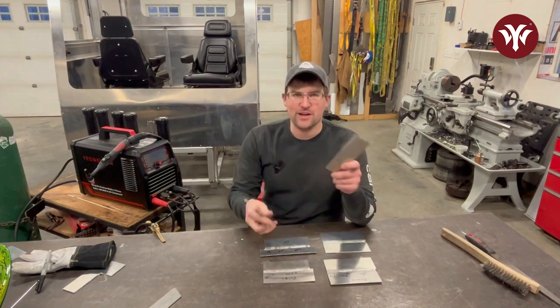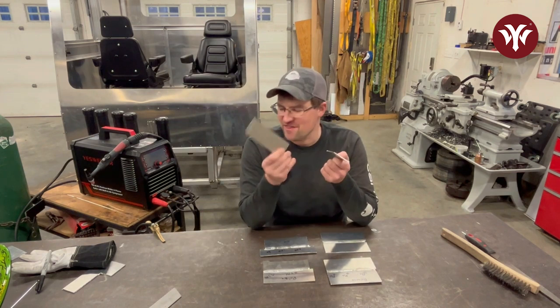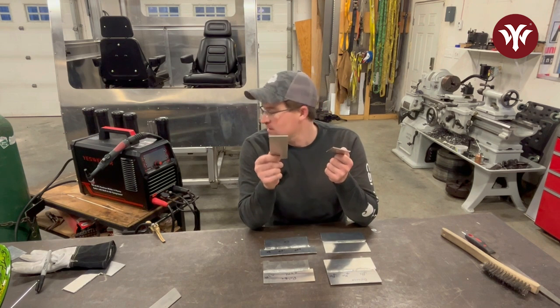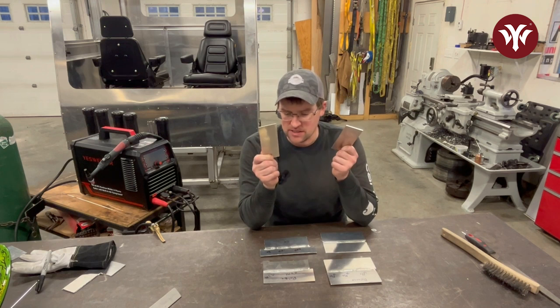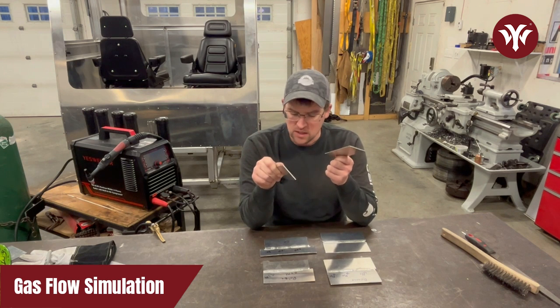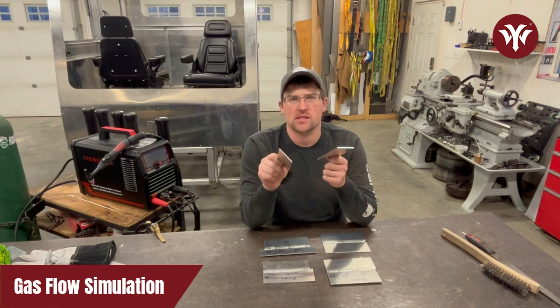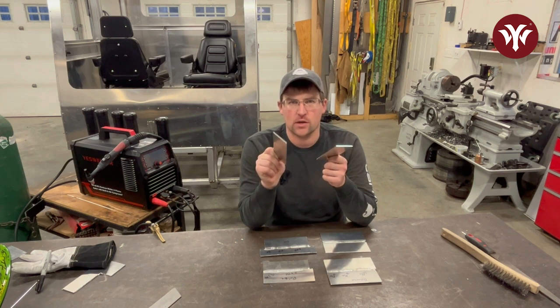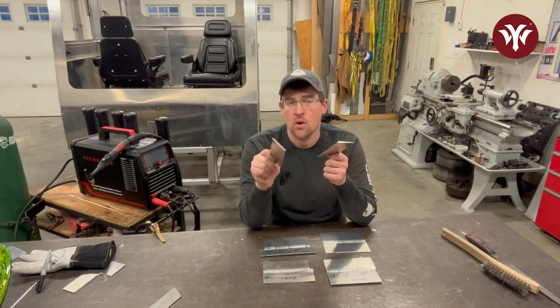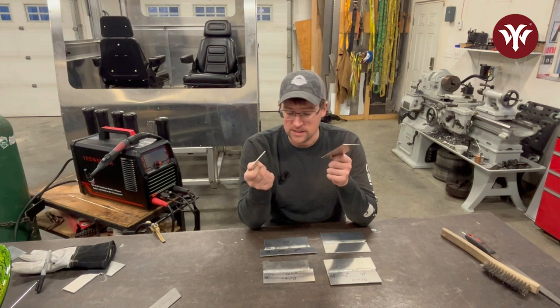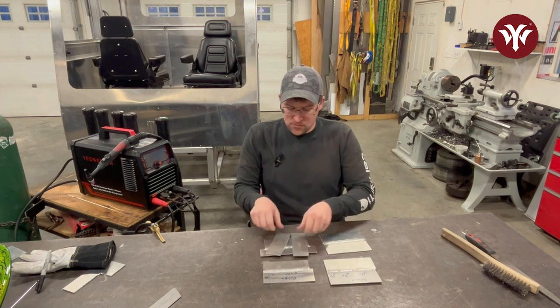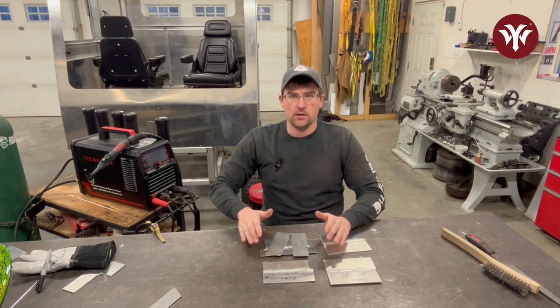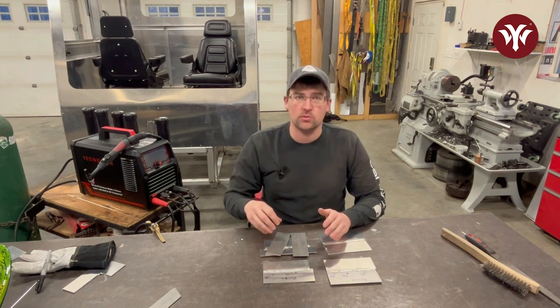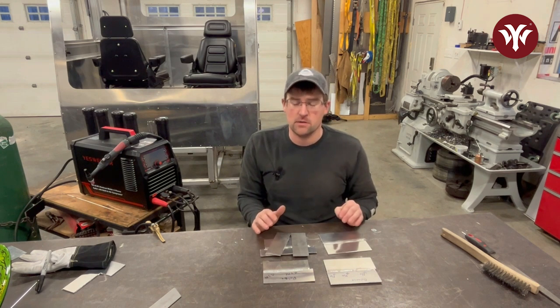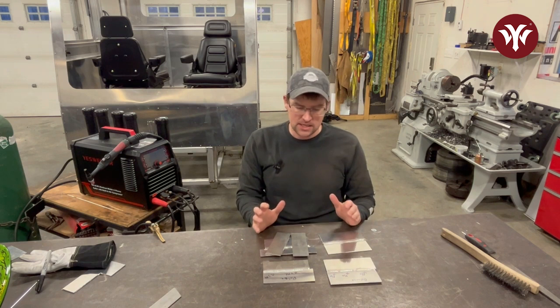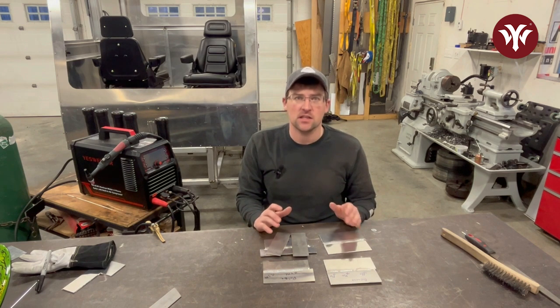All right, it's kind of fitting that I have 2 coupons left, and there was one thing I forgot to cover. Let's go through it right now, and that's gonna be like simulating a lack of gas flow, because that's probably gonna be one of the biggest things as an amateur welder that you're probably gonna fight, either contaminated gas or not having the correct gas flow, because that gas is extremely important to create a coverage over your part, because you want that arc and the molten aluminum to completely be in an inert environment, meaning no oxygen, no contaminants. It needs to happen inside an inert gas like argon.